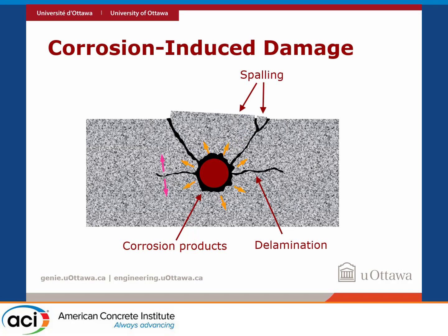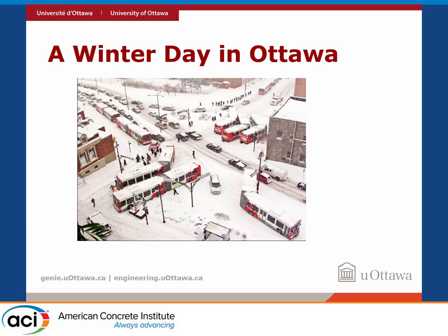So this is a phenomenon that we see quite often in aging reinforced concrete infrastructure in coastal areas. We also see it in areas with a cold climate due to the use of de-icing salts. So this is typical here in Canada. It also happens in the northern states where we use quite a bit of de-icing salts, and that's a source of chlorides that can depassivate the steel. In Canada alone, it is estimated that we use around 4 to 5 million tons of de-icing salts per year. So that's quite an amount of chlorides.